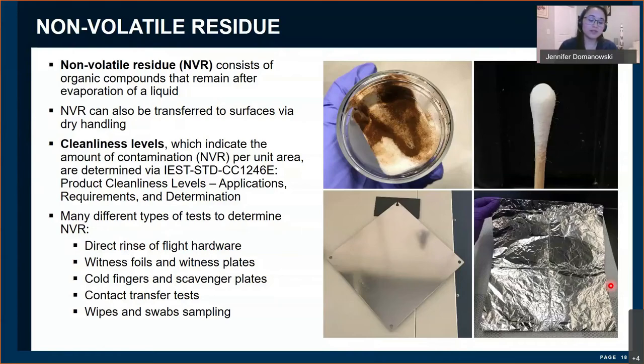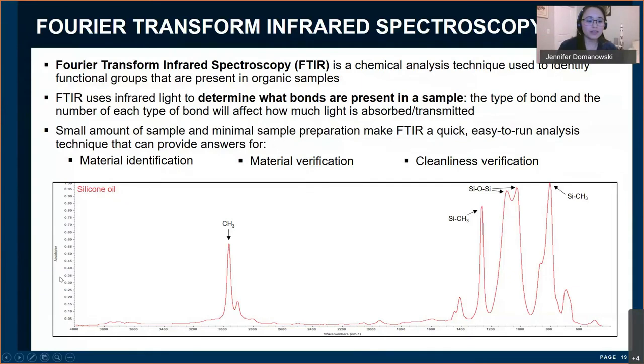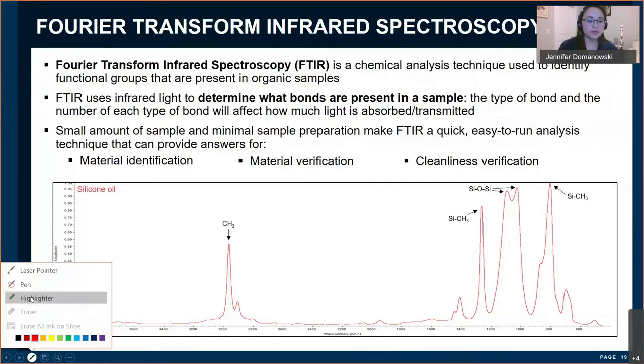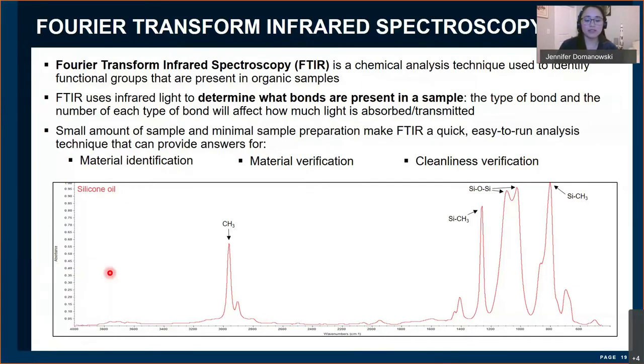Rinses of cold fingers and scavenger plates, if you remember, I mentioned those during TVAC testing. If you can see in this graph here, this is a typical signature that we get for silicones, and you can see each of the peaks represent different bonds that are in the sample. So normally we're not too happy if we see a silicone signature, because that means it has silicones contamination.